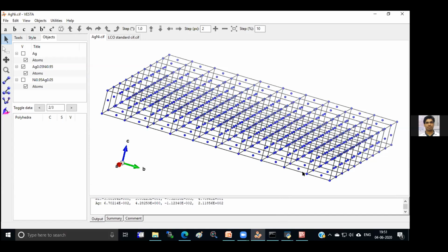Okay, so that is fine. Suppose Vesta normally gives one metal M1 one color and M2 another color. Now, whether M1 has a different oxidation state, you have to specify that, specifically tell that in the Rietveld analysis. Different oxidation states in Rietveld is slightly complicated, and people cannot do that. So nickel means nickel, and you cannot really distinguish between nickel 0 and 2 plus. Okay. Now I got it.